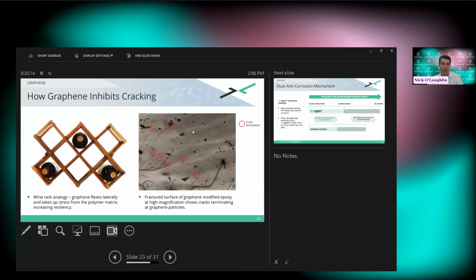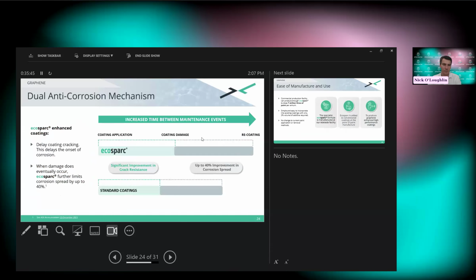We were the first, I think, to actually show this point about how graphene's working in these coatings to make them more durable. And it's basically through inhibiting cracking. So these particles, black particles on the right-hand side, are under intense magnification. They are graphene particles. And what you're seeing there is micro cracks in this coating material, in this polymer, that are starting to propagate, and they hit the graphene particle and they stop. So if you stop the micro cracking, you stop them forming bigger cracks and leading to failures of the paint. So that is a key reason why the graphene is working in these particular coatings.